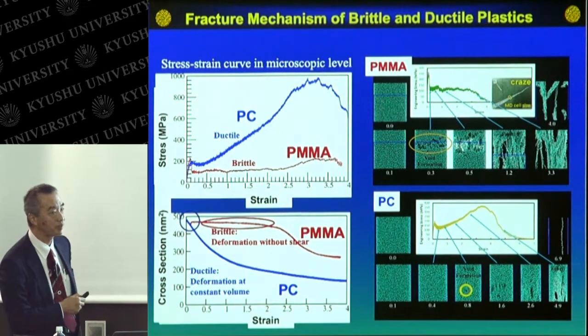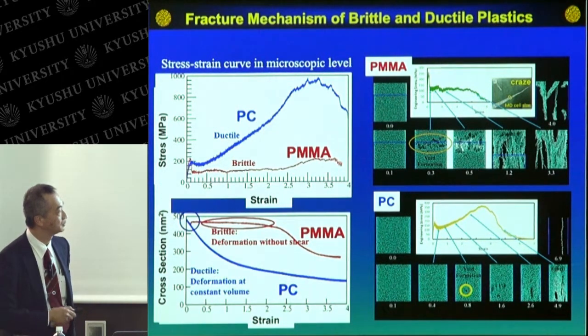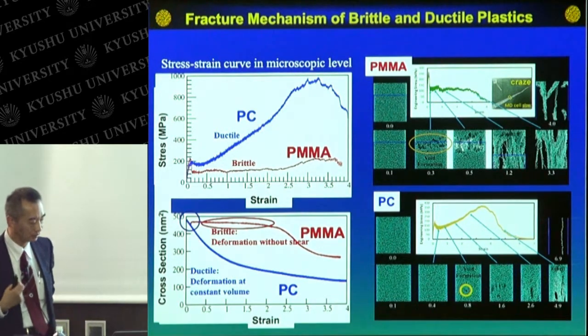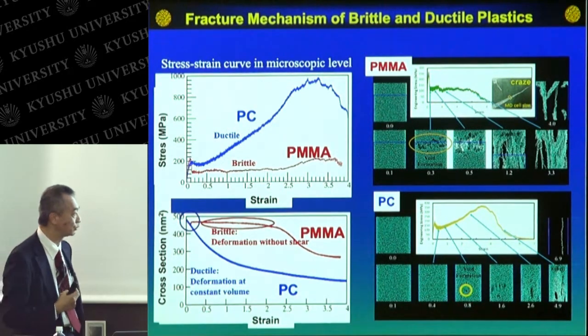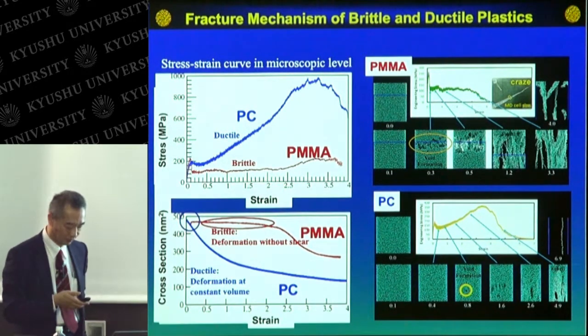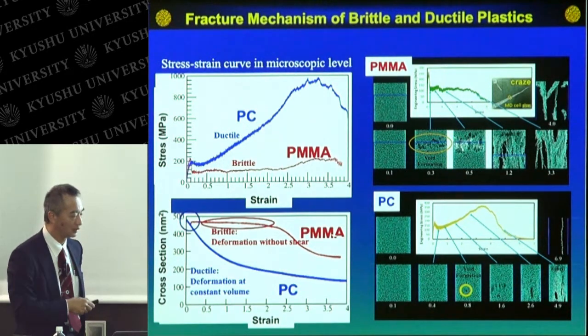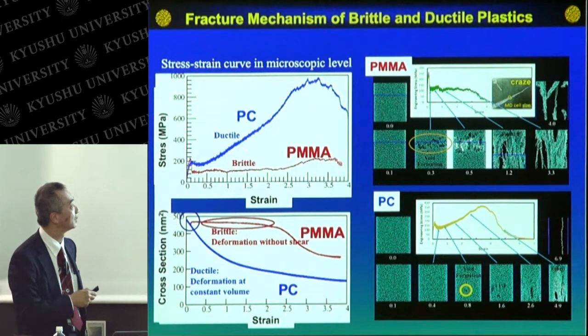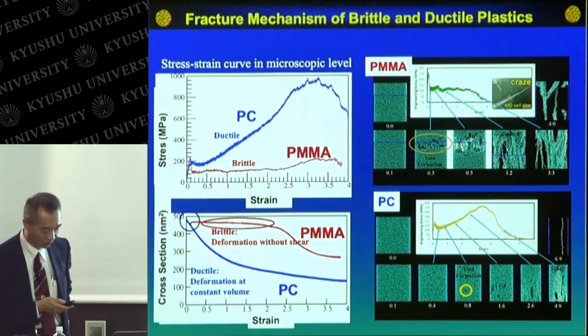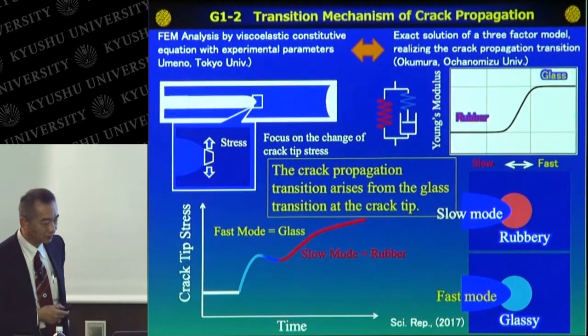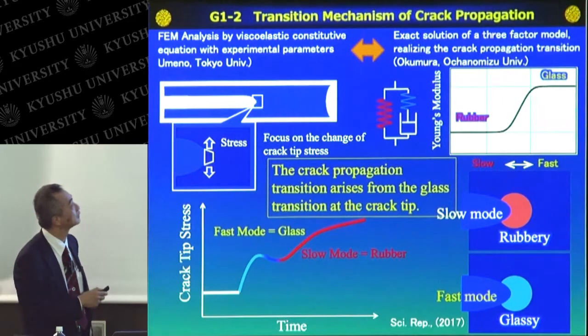Polycarbonate is a ductile polymer, a ductile transparent resin. On the other hand, PMMA is a brittle resin. And from these simulations, they obtained the essential reason of polymer fracture, which produces the difference between ductile and brittle polymer resins. Okay. And so we tried to understand the transition mechanism of the crack propagation.